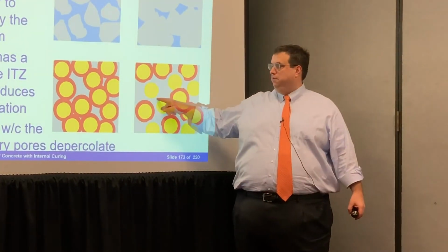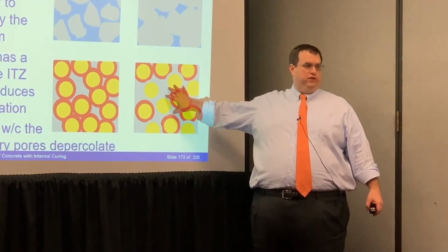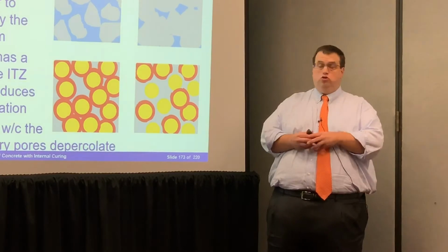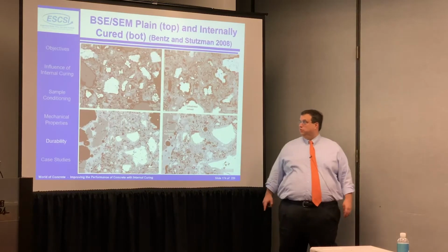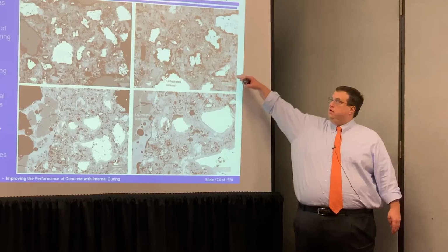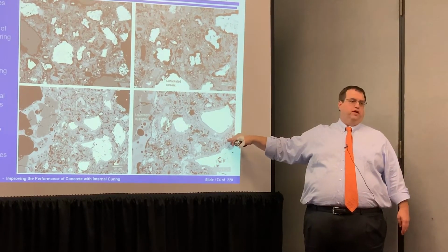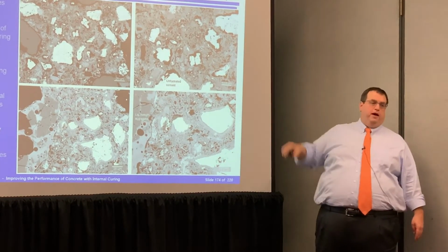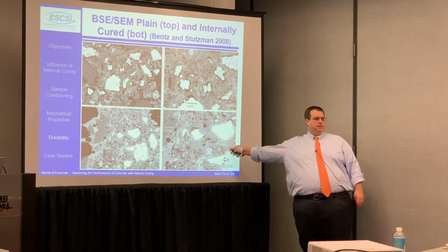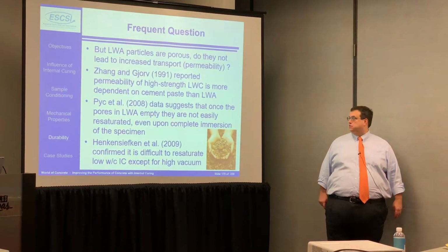We disconnect the porosity because we don't have those interfaces, so you get huge benefits from this in terms of increasing the durability of your concrete, right? Much more dense concretes, when they're hydrated more. This is concrete that ran out of water. Conventional concrete that's just sealed. This is concrete where you've got that lightweight aggregate. Dark spots are pores, holes in the system. There's a whole lot less dark spots down here, so you're getting a much more dense system. These are pictures from NIST.